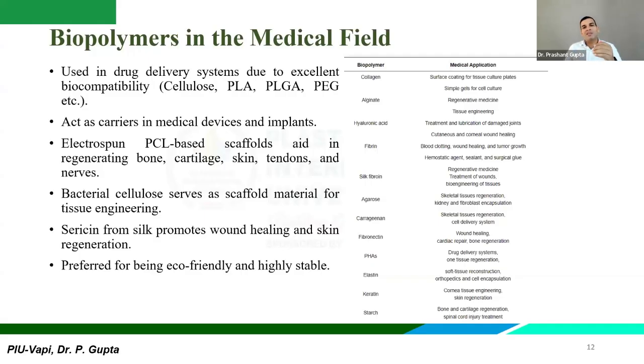So let's say if a drug is needed to be taken at night, and let's say 50 milligram is the threshold level, and the capsule is to be taken for 150 milligram because 50 milligram may only work for 3 hours. But you cannot take 150 milligram because the threshold level is only 50 milligram. So you take that 150 milligram wherein every particle will be coated by a biopolymer, preferably cellulose. And what cellulose will do is it will assimilate this drug over a certain period of time. Maybe 3 into 3 is 9 hours. So 3 times the drug that you have taken. So smart drug delivery, perfectly biocompatible in nature.